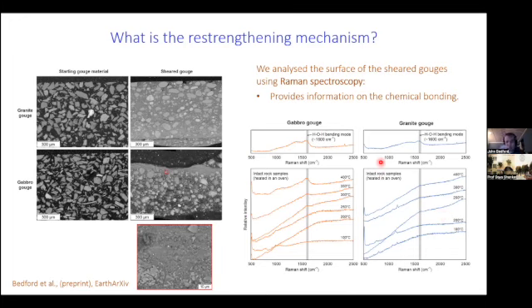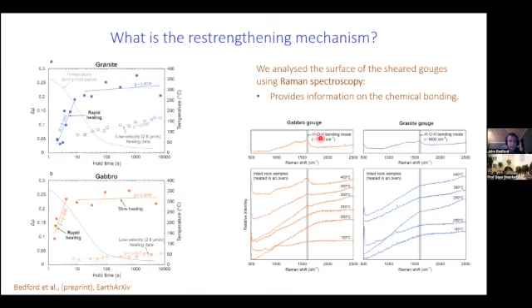And actually, the story gets a little bit more complicated here, because although we see a peak associated with adsorbed water on the surface of the materials, we don't think that adsorbed water is responsible for the re-strengthening, because as we showed, the re-strengthening occurred while the temperature was still high, above 250 degrees Celsius, where the water would be in the vapor state. The water will only reabsorb once the gouge cools below maybe around 100 degrees Celsius.